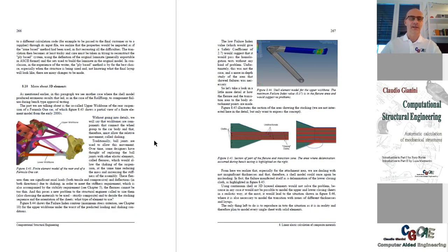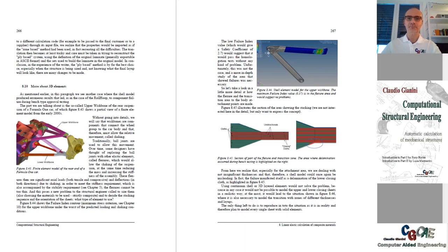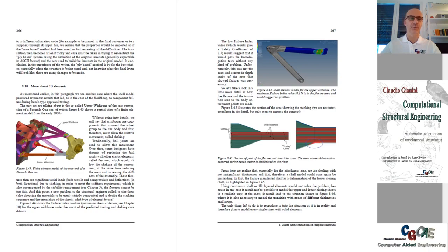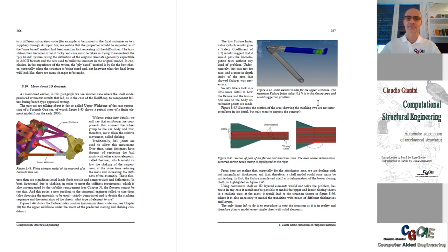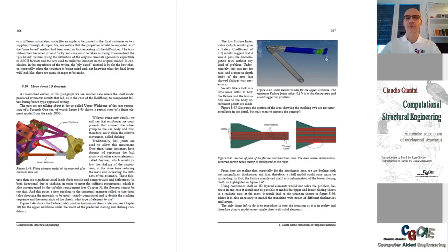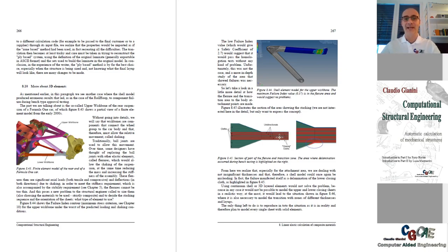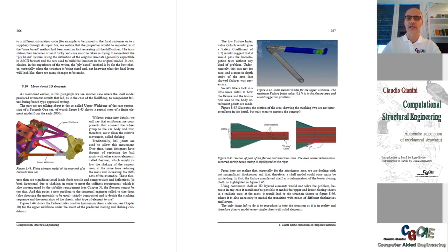Then there is another example where shell model failed. It's coming again from motorsport, Formula 1. Since the beginning of 2000, the spherical joints of the wishbones, the elements which connect the wheel group to the car, were substituted by flexible elements, the so-called flexures. Here we can see the area, the transition between the leg itself and the connection to the chassis or to the gearbox depending if it is front or rear. This part is the flexure which needs to be thin to bend but needs to be strong to resist the actual loads. In this particular case at the test bench we had the failure of this area here where the outer plies were detaching from the rest of the package.